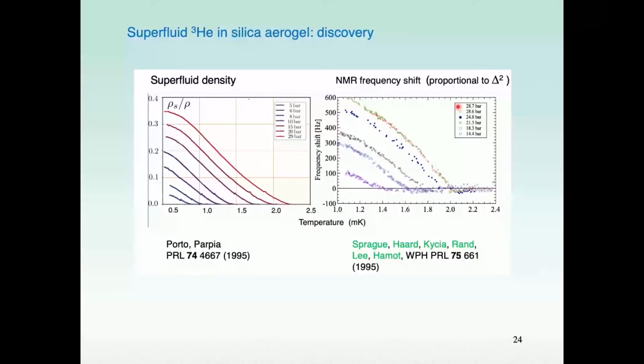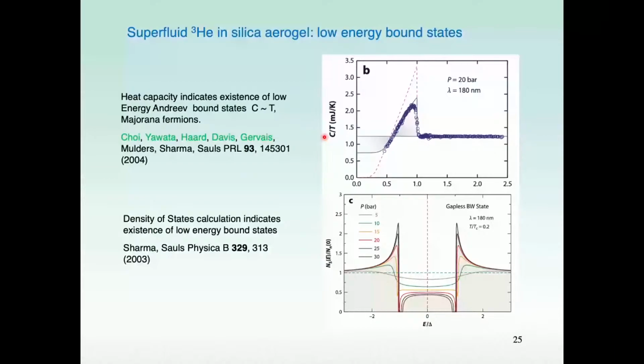In addition, the heat capacity, measurements of the heat capacity in the same environment of helium-3 in the silica aerogel, show a suppression of the transition temperatures as a function of pressure. And in particular, the jump in the heat capacity is pushed down here. I'm showing it's about a factor of 2. And interestingly, to conserve entropy, not having gone down to rather low temperatures, but nonetheless to conserve entropy, the prediction is that there has to be a limiting value for the heat capacity scaling with temperature rather than going to 0 as might be expected. And that limiting value corresponds to the Andreev bound states. And in the theoretical calculations of the density of states, here again by Jim Sauls with Priya Sharma, they show the low-lying density of states associated with these bound states.